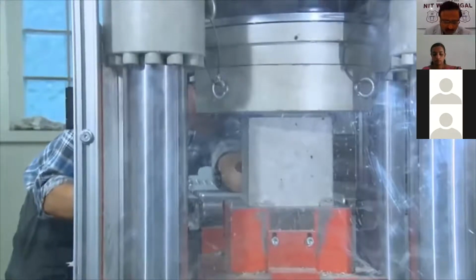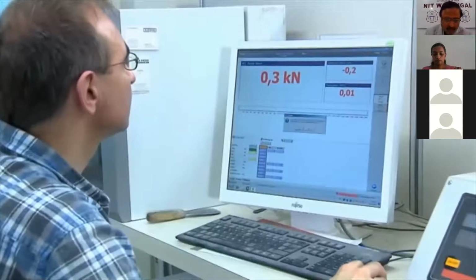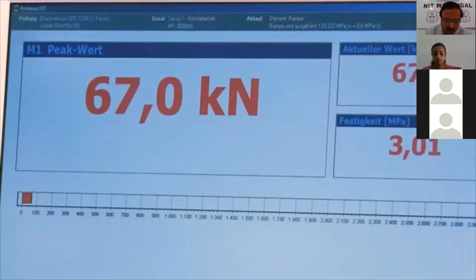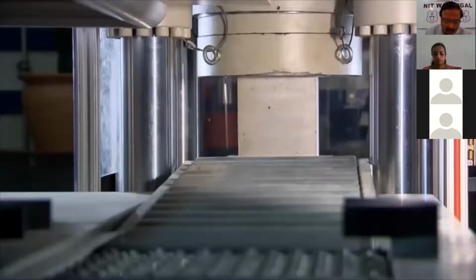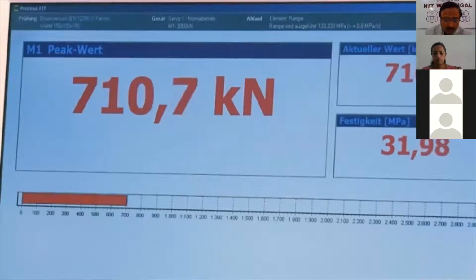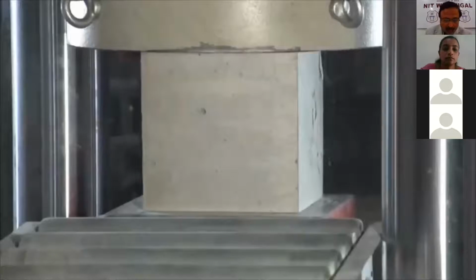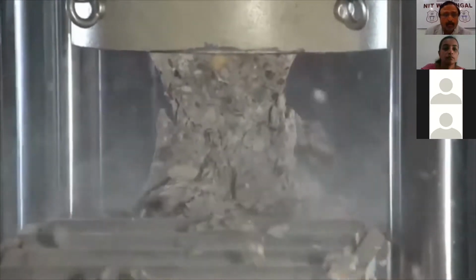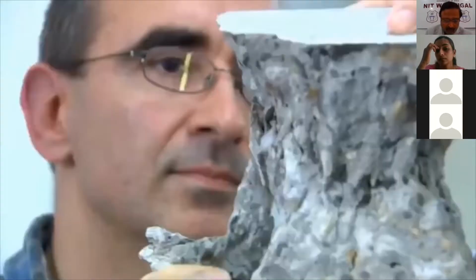They're preparing a so-called compressive strength test. A sample cube with an aggregate of nearly 100% concrete rubble is positioned in the device. Then pressure is slowly applied. The currently admissible strength class requires the sample cube to withstand a force of well over 700 kilonewtons. That equals the weight of more than 60 mid-sized cars. The test shows that recycled concrete made of 100% recyclate can withstand the required strain. That means it could contain twice as much concrete rubble as previously allowed by law.